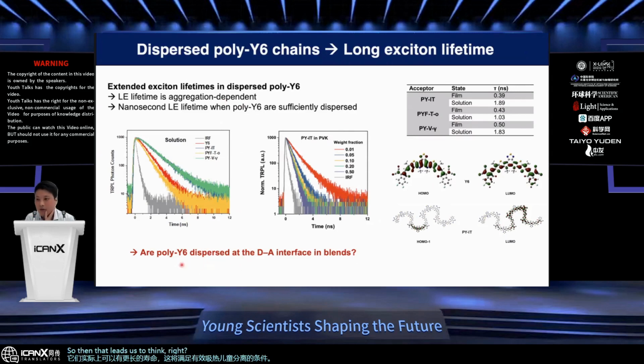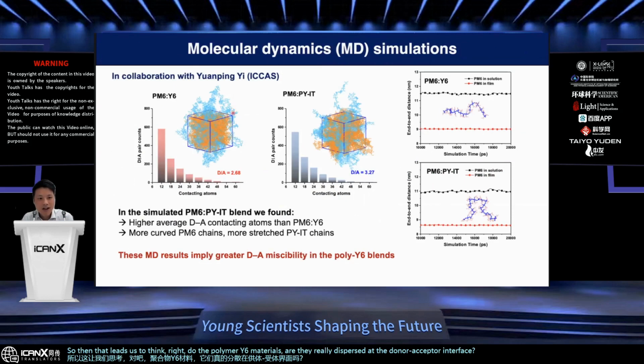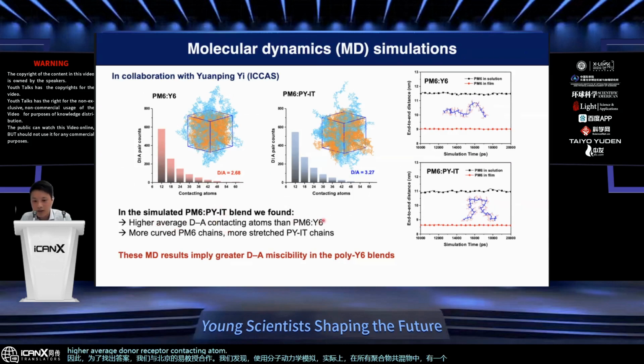do the polymer Y6 materials, are they really dispersed at the donor-acceptor interface? So to find out, we collaborated with Professor Yi from Beijing. What we found, using molecular dynamics simulation, was that indeed, in the all-polymer blends, there's a higher average number of donor-acceptor contacting atoms compared to the small molecule counterpart. We also find that the PM6 are a lot more curved and the PYITs are a lot more stretched. So, these are basically fancy quantitative terms to describe that.